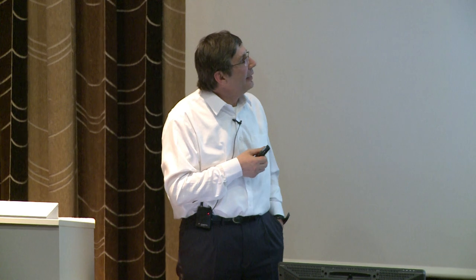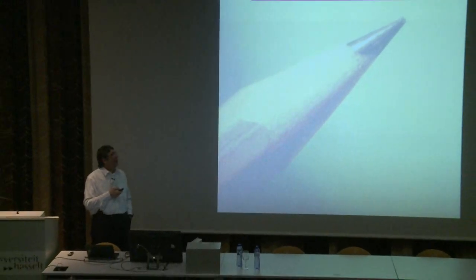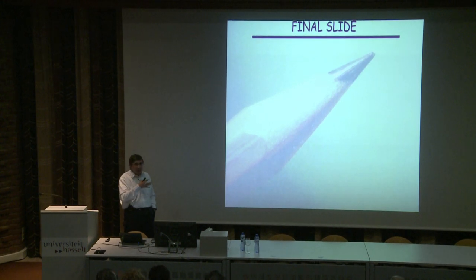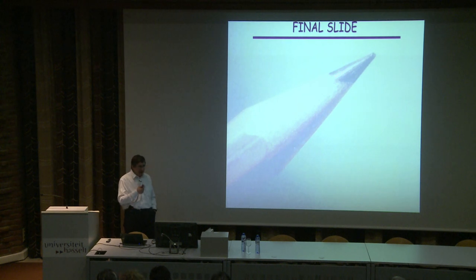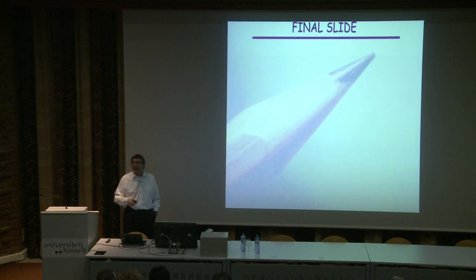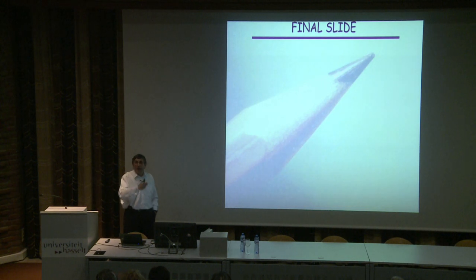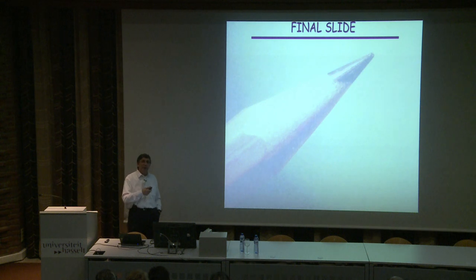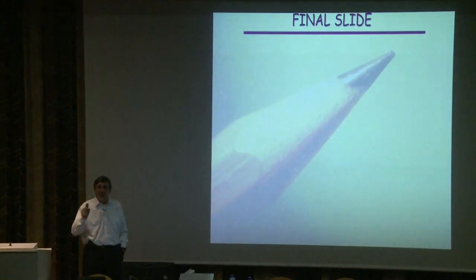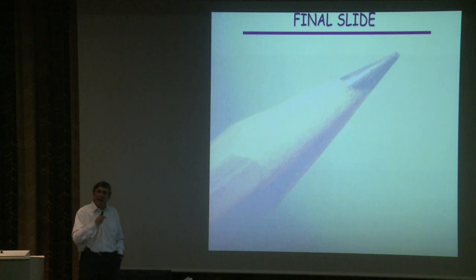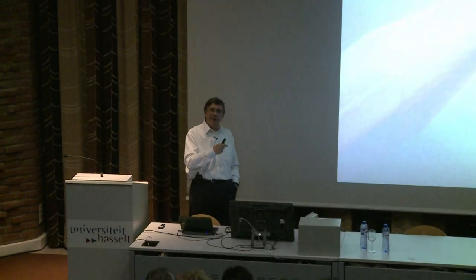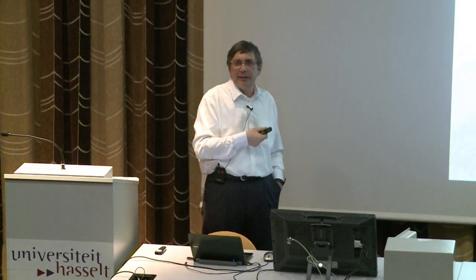And my final slide, after saying that applications are probably coming but the extent remains unclear, is to summarize this by the picture of a pencil. If you take a pencil and a piece of paper, draw a line. It's a pencil trace. It's dark because the pencil contains graphite, and graphite slides off by this scotch, as you saw from scotch tape, very easily. Those remnants of graphite are left on the surface. If you take a microscope or even a magnifying glass, you look through this pencil trace and see pieces of graphite left on the surface. But if you look carefully enough, you'll find some of those pieces are very thin. Some of them are even one atom thick, which is graphene.